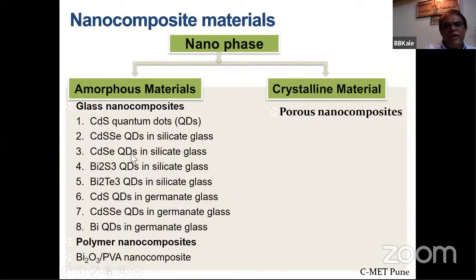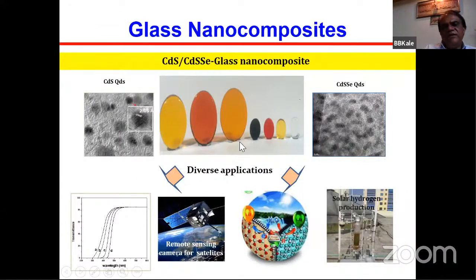And then we make quantum dots in glasses, all kinds of cadmium sulfide, cadmium selenide, bismuth sulfide, bismuth telluride, all kinds of quantum dot materials we can grow in the glass. That means you can have glass with a band gap from 3.4 electron volt to almost 1.2 electron volt. You can see here, all these glasses have different quantum dots inside them, so it gives different colors.